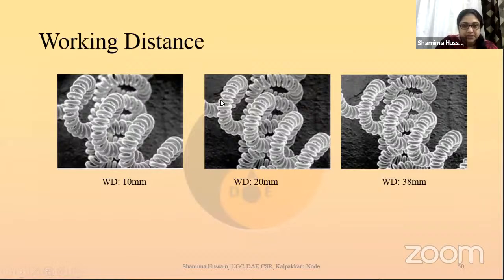When I increase the working distance to 20, please see this area, then you can make out better. Something extra, a spiral part, is visible here. That is, I've increased the view slightly. And I put the sample stage even further down, 38 mm. I can see a wider area. This is how working distance plays.